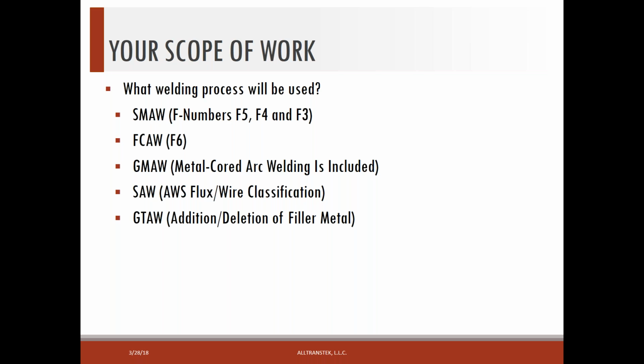Those electrodes are identified by an F number, and that particular F number is F6. So if I have a process, flux core arc welding, from the standpoint of F numbers, I can use any F6 electrode when I'm qualifying a procedure, just looking at that for an essential variable. Under gas metal arc welding, metal core arc welding is included in that. And then for submerged arc welding, we'll have to look at the AWS flux wire classification to determine whether we have adequate tensile strength in the filler metal, if we expect it to meet the required notch toughness properties. That's the classification for the submerged arc electrodes and fluxes.